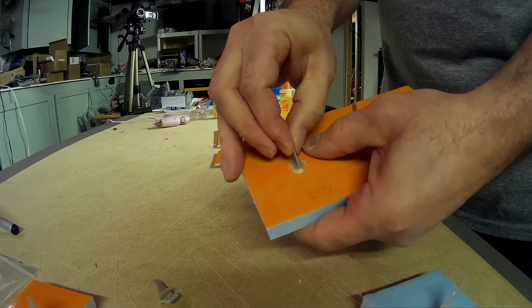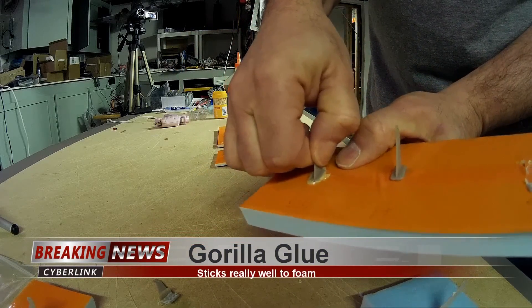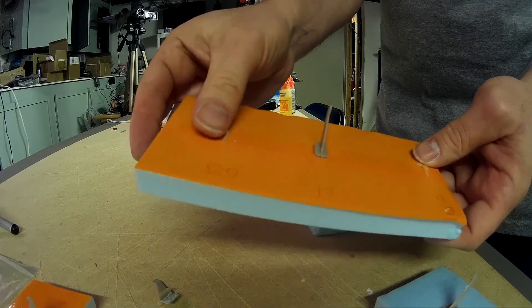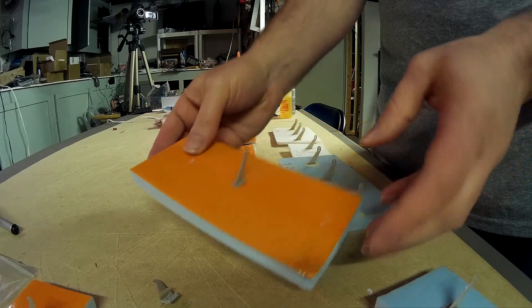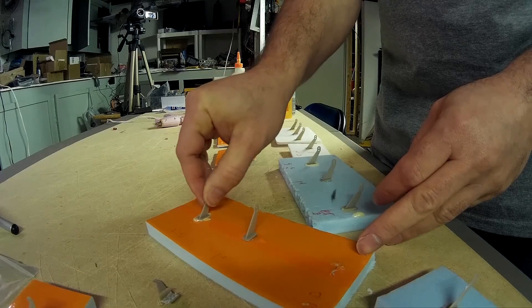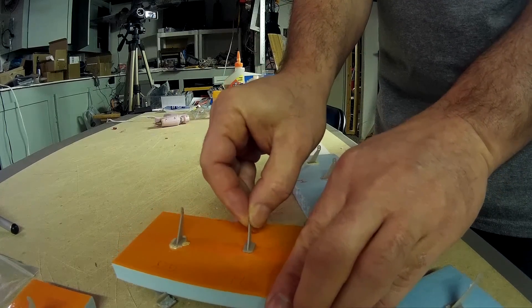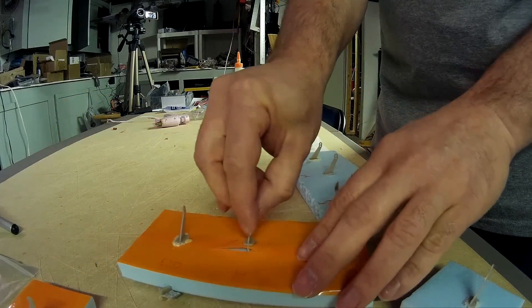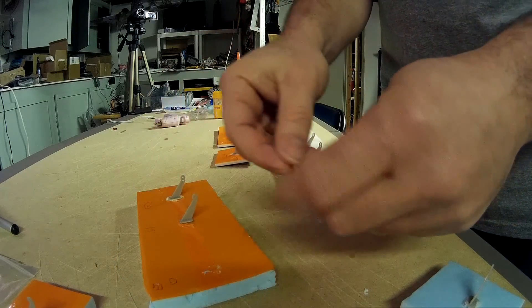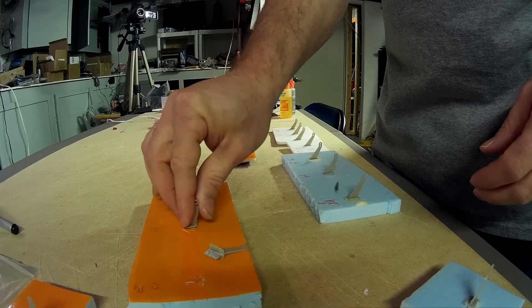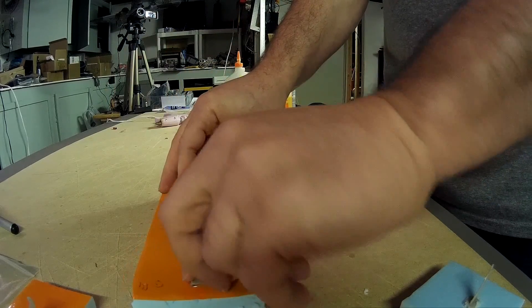Okay, now the Gorilla Glue. It's pretty sturdy. And it came out now. Here's what I've noticed before with the Gorilla Glue. You see how you've got a complete piece of Gorilla Glue there, and it didn't stick to the packing tape. So we've got some interesting combinations here. Now the only one that didn't come off, even with a fairly significant pulling, you see how I ripped the packing tape, was the hot glue. But I don't think the hot glue stuck the best to the foam. On packing tape in foam, the hot glue is as good as anything else. The epoxy, I think, was slightly better than the Gorilla Glue, and the CA was the worst of the bunch.